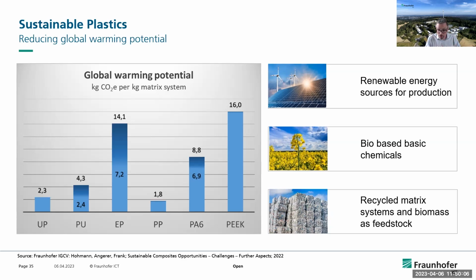Using renewable energy sources always leads to a reduction of the environmental footprint, but especially for the high-performance materials, the replacement of fossil-based with bio-based chemicals like aniline is under investigation. However, in contrast to the carbon fibers, lots of components contribute to the global warming potential. The reduction potential has certain limitations. So we have to use recycled material and bio-based feedstock.